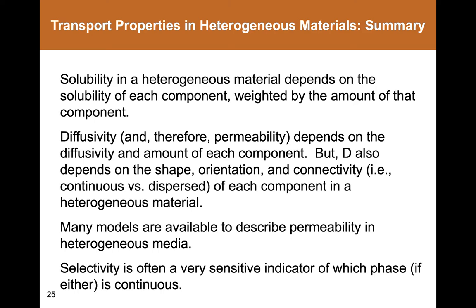There are a number of models of transport in such heterogeneous materials. Typically, the solubility behaves rather simply, that is, as a weighted average of the amount of each component and the solubility of the penetrant in those components. The diffusion coefficient, however, also depends on shape, orientation, and connectivity. And this is why the permeability then in turn depends on shape, orientation, and connectivity of the components in a heterogeneous material. As we've seen previously, selectivity can be a very sensitive indicator of which phase is continuous.